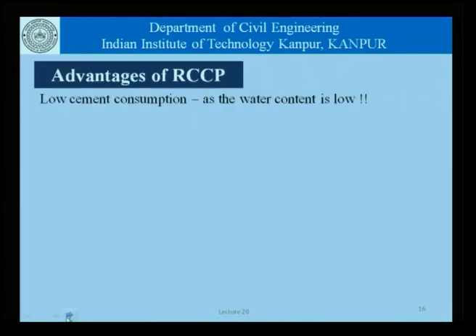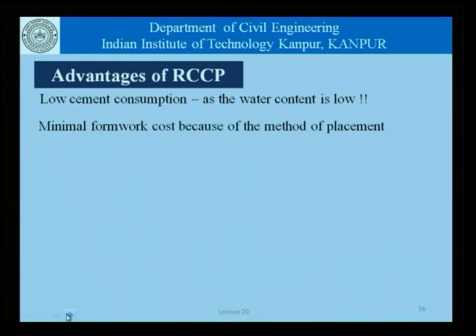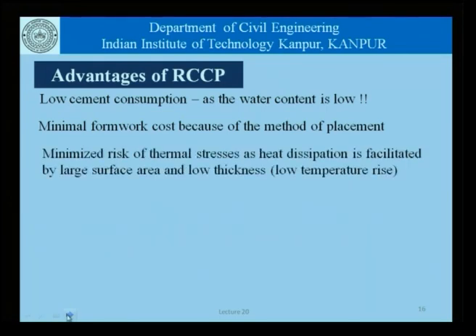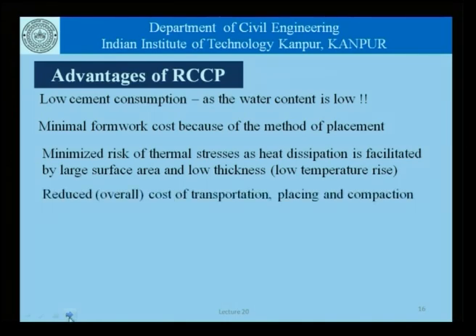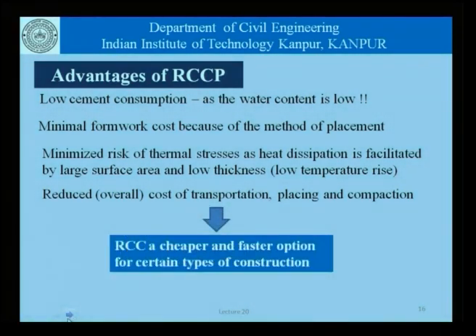The advantages of RCC include low cement consumption because the water content is very low, minimal formwork cost because hardly any formwork is required except at the edges, minimized risk of thermal stresses as heat dissipation is facilitated by the large surface area and smaller thickness — meaning low temperature rise and virtually no thermal gradients — and reduced overall cost in terms of transportation, placing, and compaction. Roller compacted concrete gives a cheaper and faster option for certain types of construction.